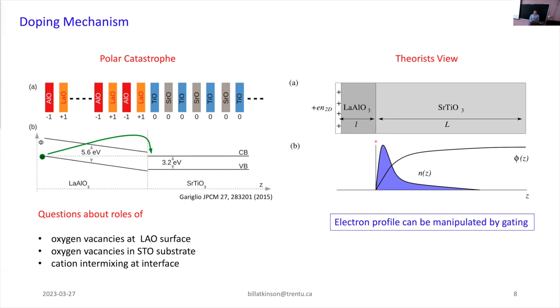Now there is this cartoon for why this happens. It's called the polar catastrophe model, and the idea is that the lanthanum aluminate is a polar material when you grow it along the 100 direction. So you have these alternating layers of lanthanum oxide and aluminum oxide that are nominally plus one per 2D unit cell and minus one charge per 2D unit cell. And so you get voltage differences between these layers. And as you grow more and more unit cells, the voltage difference between the interface and the surface grows roughly linearly with the number of unit cells of lanthanum aluminate.